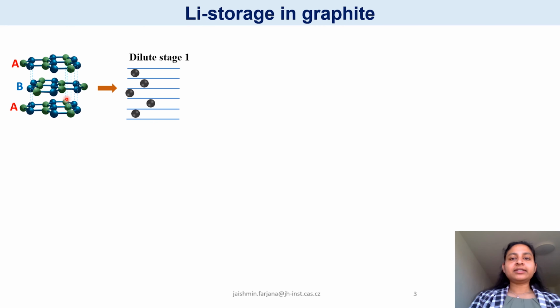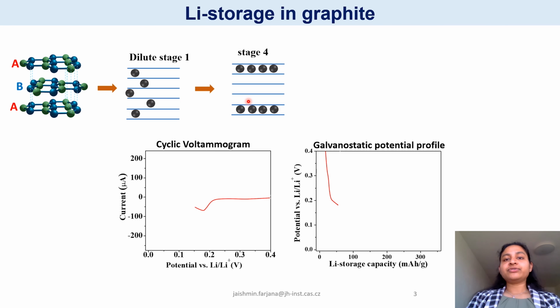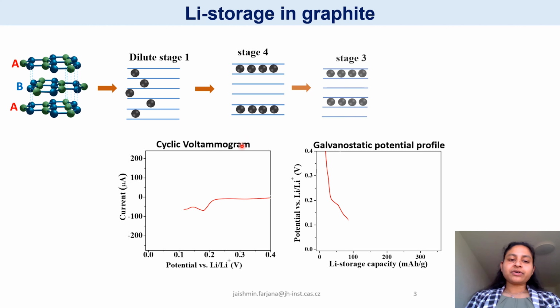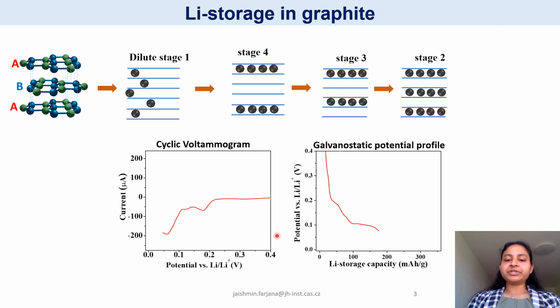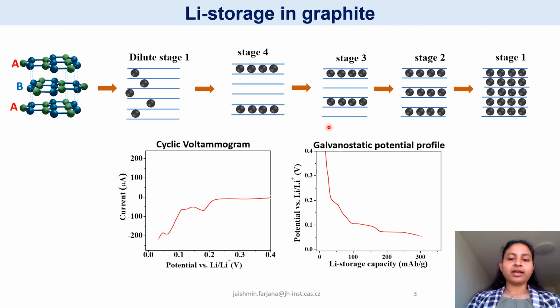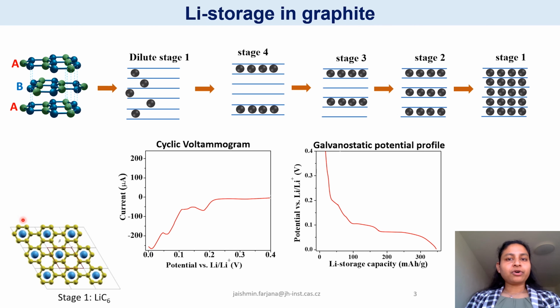Let's see how lithium is stored in the graphite. When the battery is charged, lithium intercalates in between the graphene layers, graphite layers, and the concentration gradually increases. Because of that, we could see peaks appearing in the cyclic voltammetry or potential plateau in the galvanostatic potential profile. This is the final product that can be formed from lithium and graphite.